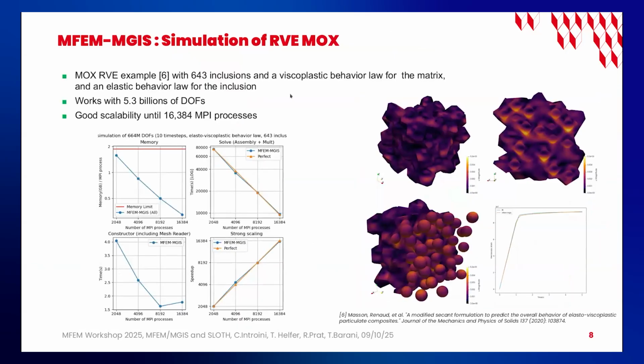Another example, just to show that we do a lot of periodic computation at the RVE level. It's a description of a specific nuclear fuel called mixed oxide fuel, which contains uranium and plutonium. And in this case, we just modeled a matrix and an inclusion, and we try to compare performances of and make some verifications of MFEM-MGIS against fast Fourier transforms, and also try to measure the performances of MFEM-MGIS on our clusters with good strong scalability, as shown on this figure. So this work on the solvers was mostly done by Raphael.